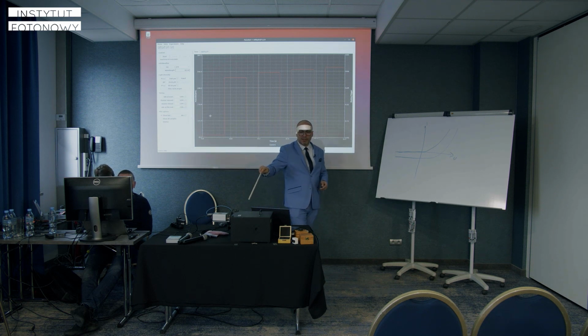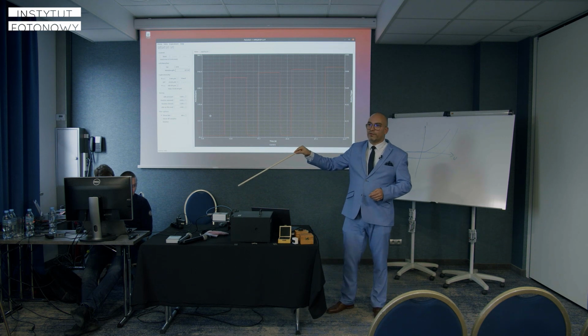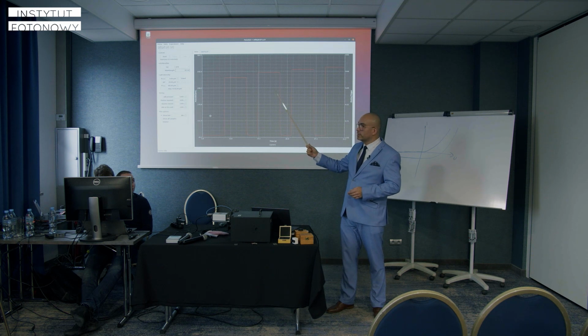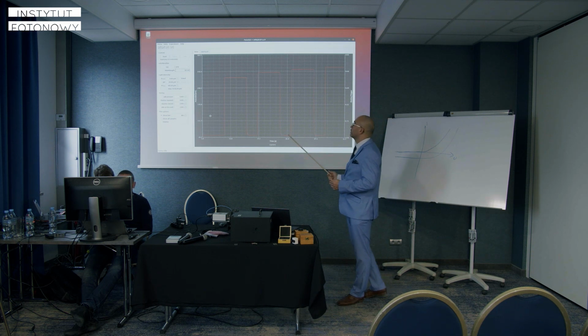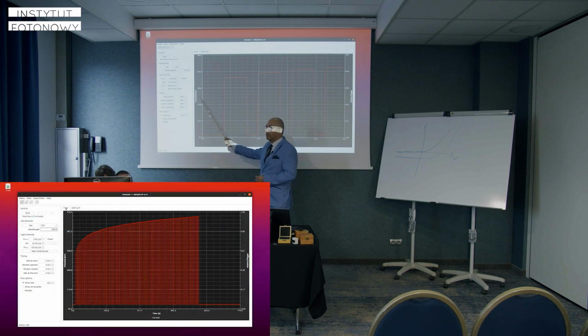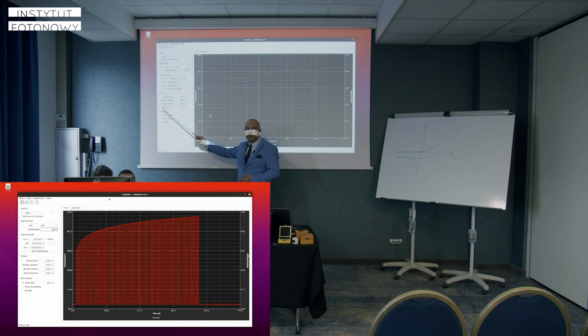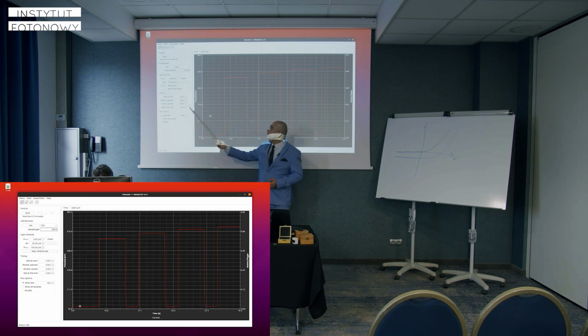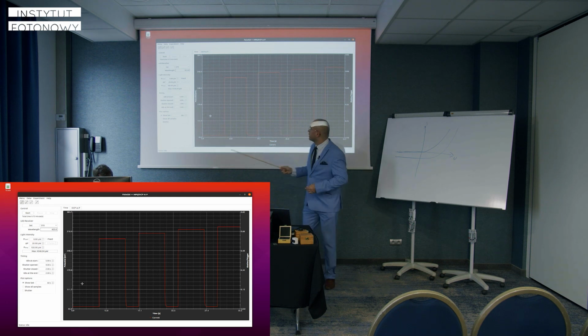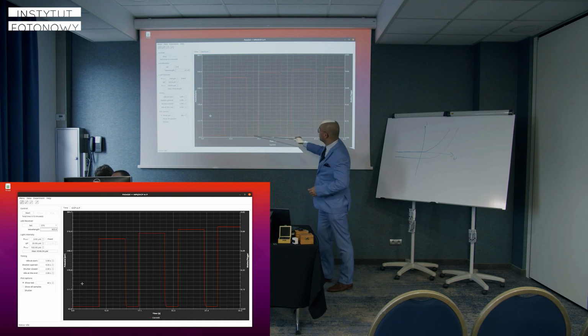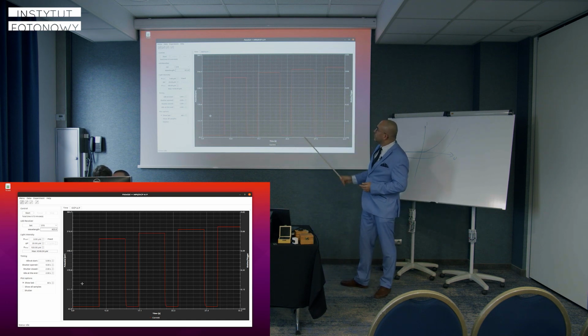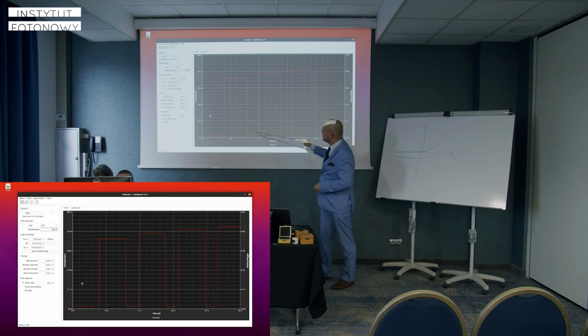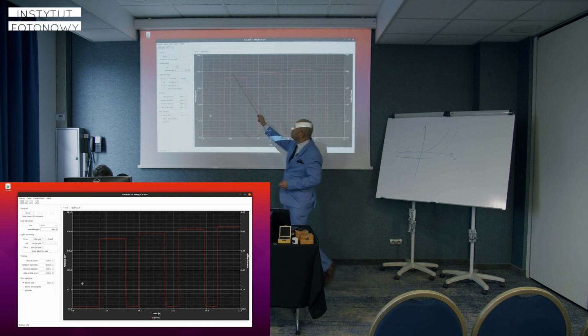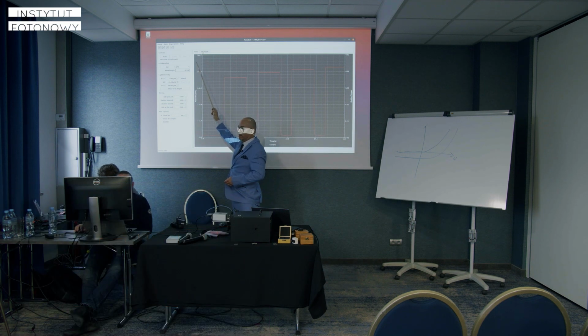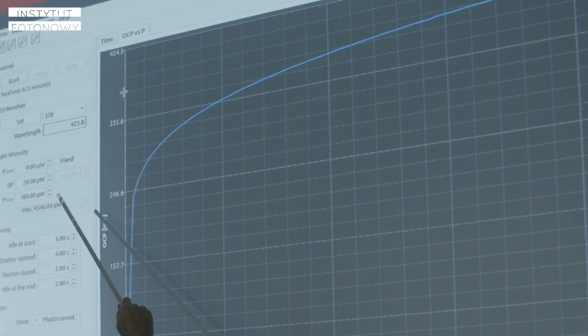There is no mechanical shutter like in the case of the large photoelectric spectrometer. We control it just electrically. We don't have to use a mechanical shutter, but this is just a name for this feature. We open the shutter for 4 seconds, then we close the shutter for 2 seconds. Here we see 4 seconds and 2 seconds, and we measure the difference. This value minus this value gives us the point. Let's switch to the other tab. It gives us this value for 20 microwatts, and so on.